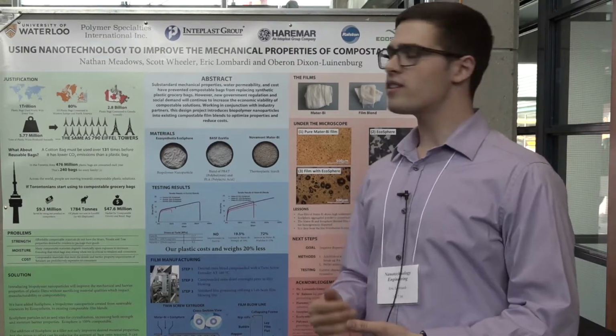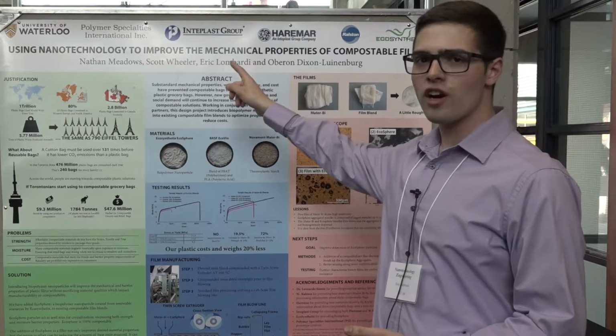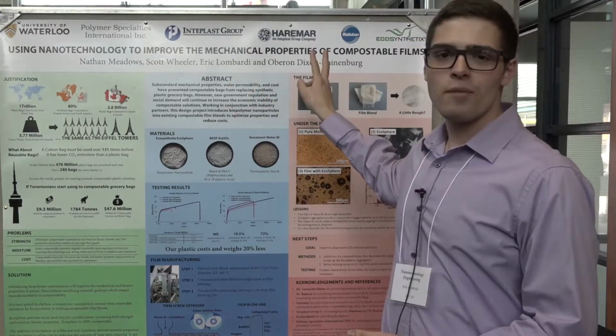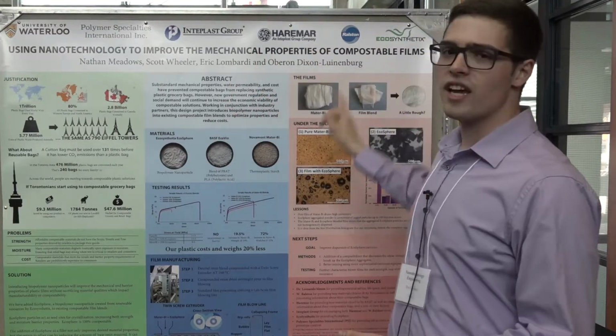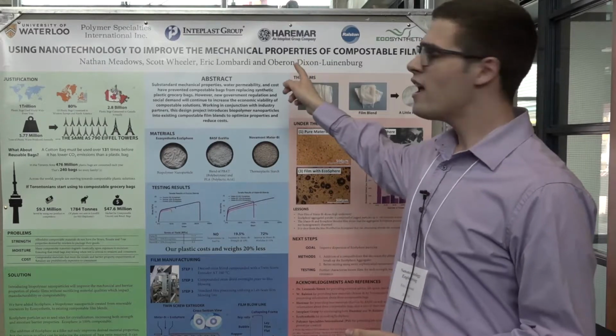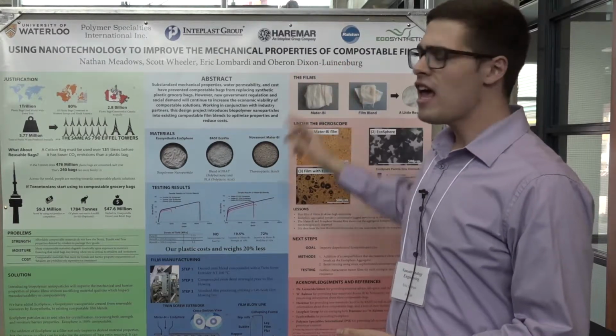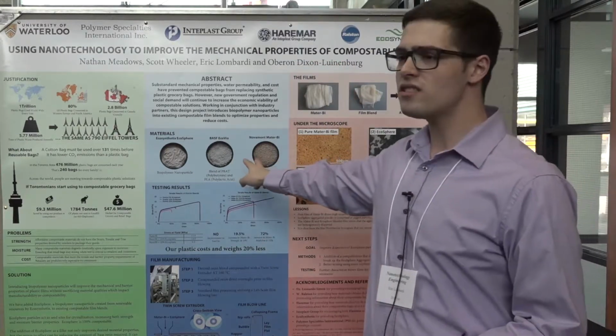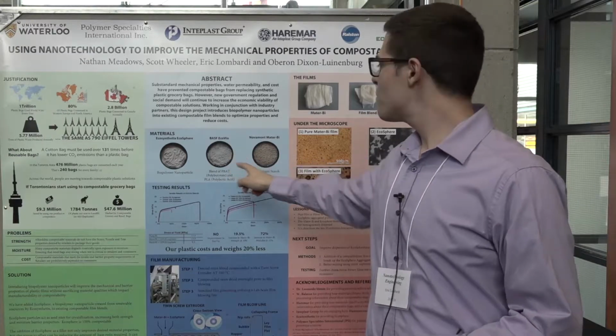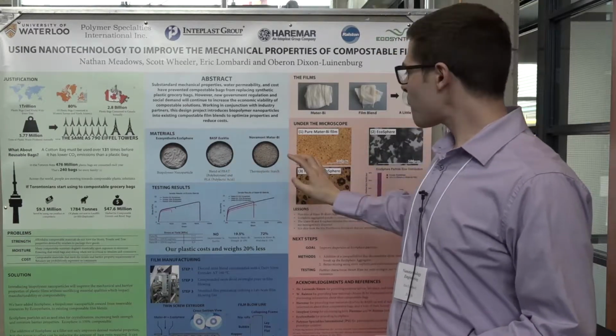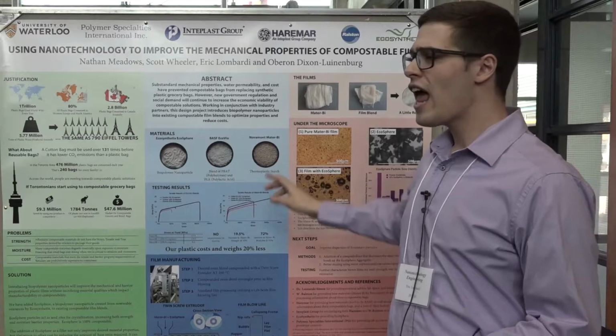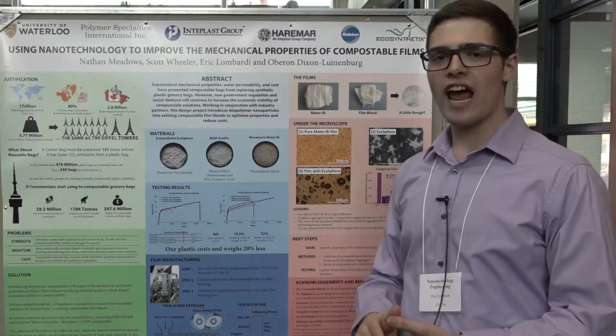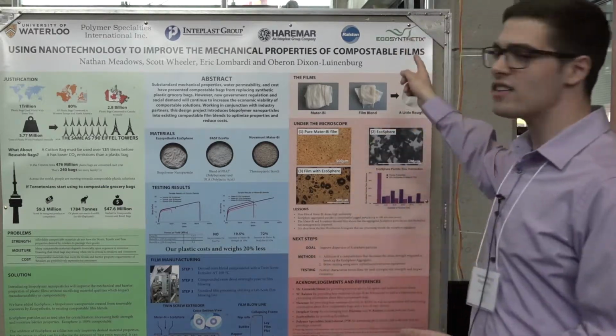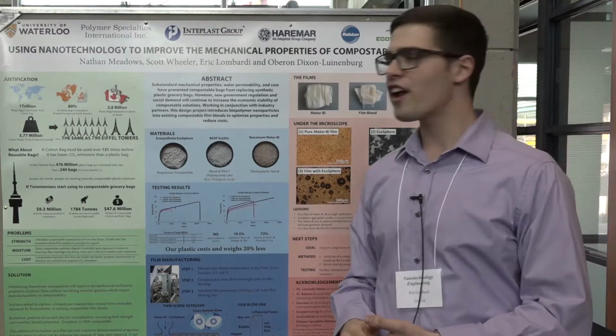We started by reaching out to Interplast Group, which is a corporate owner of 2 other companies, Haremar and W. Ralston, one which is based out of Vaughan and the other which is based out of Brampton. And we used their existing solutions, EcoVio by BASF and Novamont Mater-Bi, which is a thermoplastic starch, and we combined that with a biopolymer nanoparticle produced by EcoSynthetix, which is based out of Burlington, Ontario.